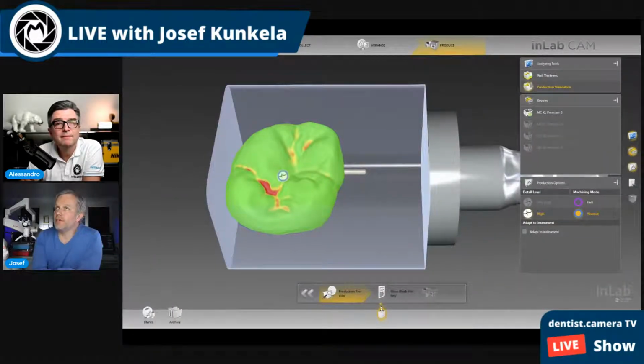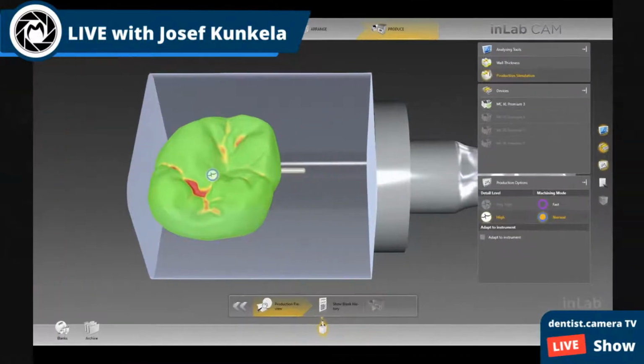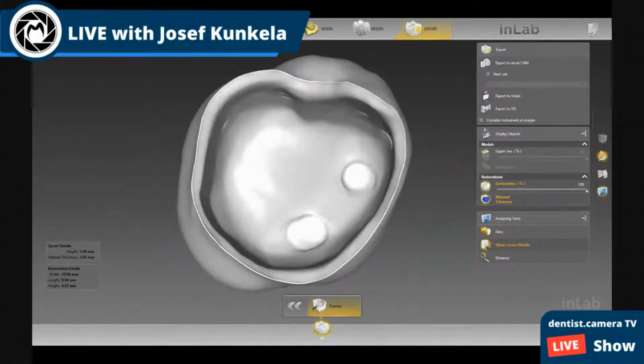The first limitation, and also why I have decided to try to implement printing more for permanent restorations, is the occlusal surface, as I mentioned before. The software shows you the limitation of the burrs, which is impossible to mill from the external side, the occlusal surface, and also from the internal surface, because your preparation has to be very smooth and very rounded to avoid burr interaction. It's usually a step burr going inside your restoration, and this burr touching and often over-milling the internal surface can be responsible for later cracks.